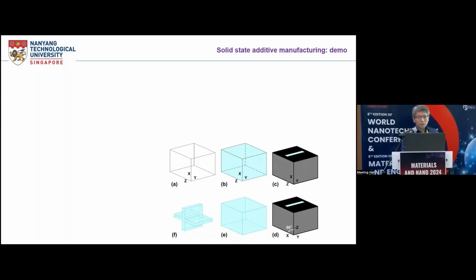We will start with a transparent container and then put the liquid material inside of it at room temperature. At room temperature, it becomes solid, okay? Because it's a very special type of hydrogel. And we place the mask on top, and then UV crosslink from top.